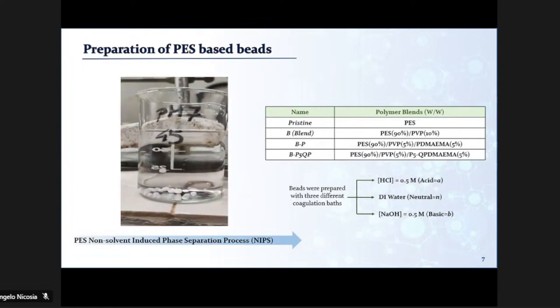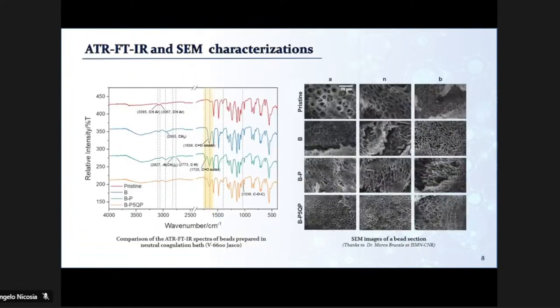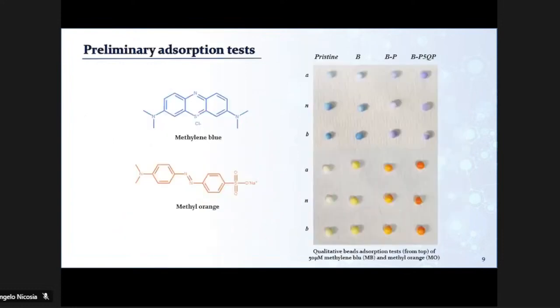We characterized all the developed beads by ATR-FTIR spectroscopy to confirm the functionalization of the beads, as well as SEM images. By SEM images, it is possible to observe a change in the morphology of the beads thanks to the different functionalities of the polymeric blends employed. Finally, to test the adsorptive properties of these systems, we preliminarily tested the performances towards the removal of 2 model organic dyes, methyl orange and methylene blue.